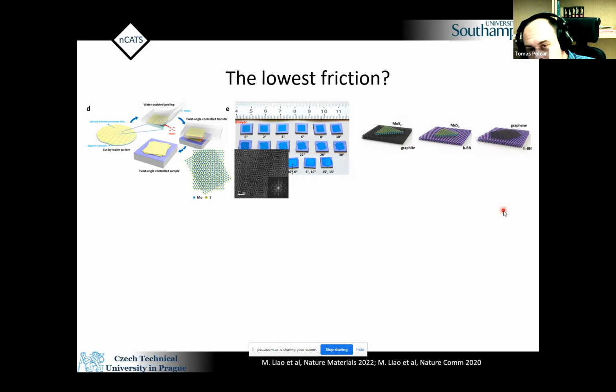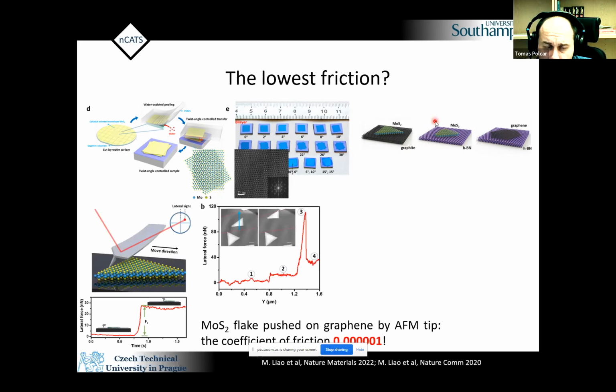And you can even select to some extent the rotation, especially for these two, because they have a very high lattice mismatch, so they are basically naturally incommensurate. I will focus on this work on molybdenum disulfide and graphite. What we did was really to use our slider, and we just pushed the flake. As you can see here, we started here, we were pushing the flake, and you see it ends up here.